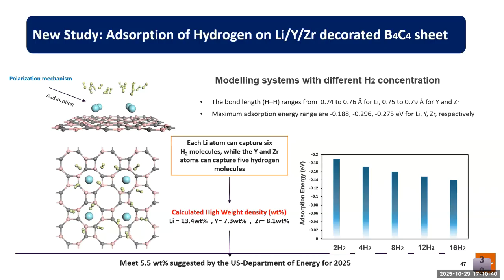And I think the most important highlight is that each lithium atom can capture 6 hydrogen molecules, while each yttrium and zirconium atom can capture 5 hydrogen molecules. If you calculate the weight density, it comes out with 13.4 weight percent, 7.3%, and 8.1%, all exceeding even the U.S. Department of Energy targets, 5.5 for 2025 and 6.5 ultimate.